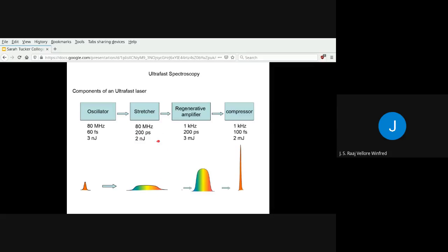Then we take the pulse coming out of the stretcher and use an amplifier. This amplifier amplifies the power. As you can see, it amplifies the power from 2 nanojoules to 3 millijoules, but we still have 200 picoseconds. Now, how do we reduce the pulse width? We take the pulse out of the regenerative amplifier and send it to a compressor. The compressor compresses the pulse from, let's say, 200 picoseconds to about 100 femtoseconds.